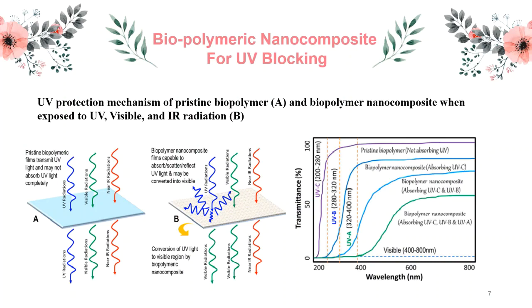Biopolymeric materials like chitosan, cellulose, and starch are derived from natural sources with good biocompatibility and biodegradability. The pristine biopolymer materials may or may not be capable of absorbing UV radiation, which depends on the intrinsic components of the polymers. This is due to the lack of pi-pi transition, and hence absorption is difficult or very weak in the UV region. Thus, pristine biopolymeric materials may allow all UV, visible, and near IR radiation to pass during exposure.